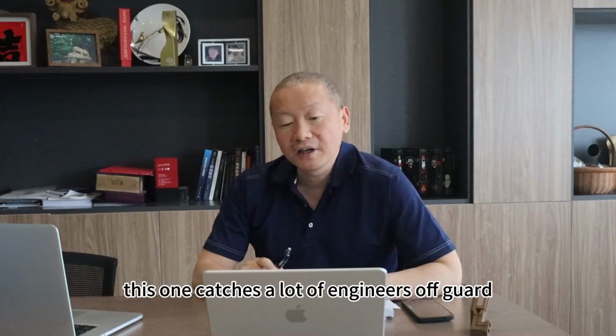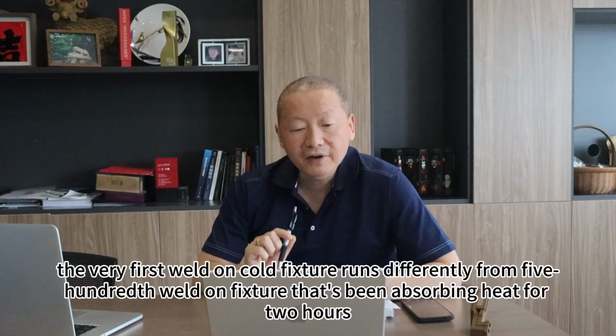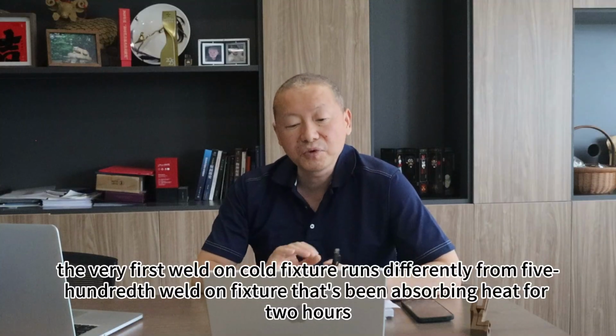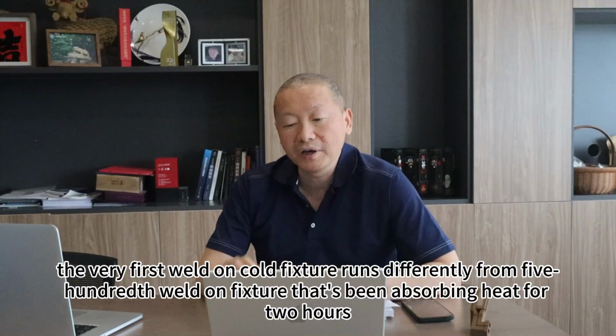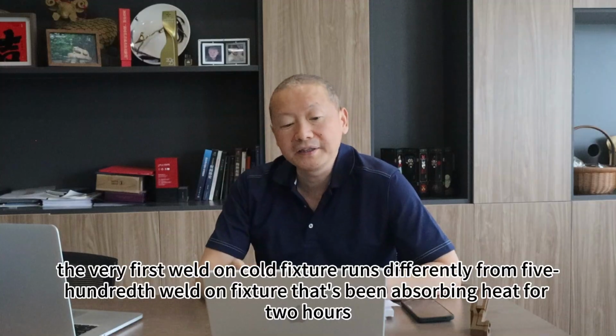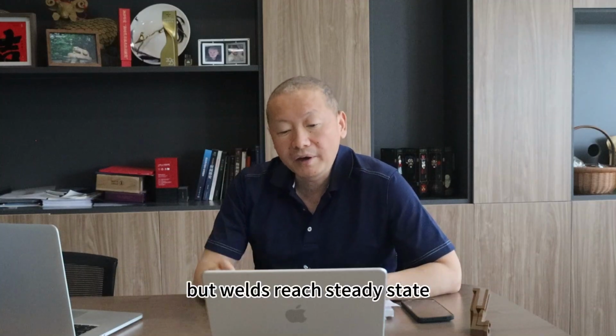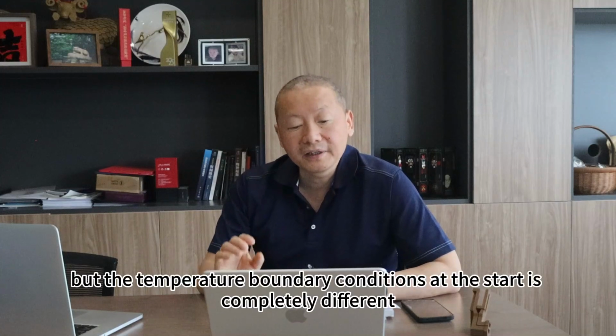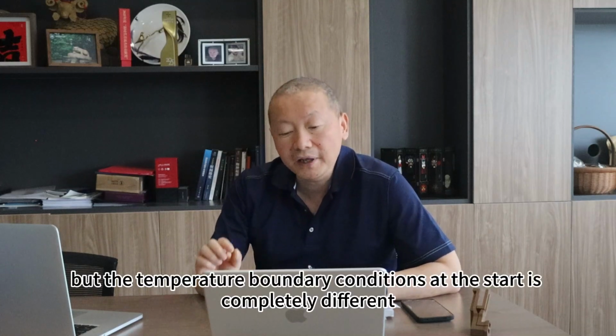Third, the thermal accumulation. This one catches a lot of engineers off guard. The very first weld on a cold fixture runs differently from the 500th weld on a fixture that's been absorbing heat for 2 hours. Both welds reach phase 3 steady state, but the temperature boundary conditions at the start are completely different.